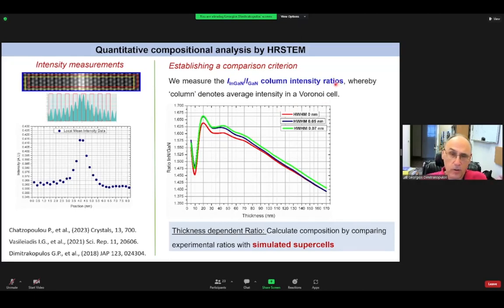But you have to keep in mind that it's not a straightforward thing to correlate this intensity ratio to the composition. You need to do the hard work. You need to do image simulations, because this intensity ratio, even for a certain composition, is not stable, but it changes with the thickness of the TEM foil. So you see here that this is for 100% indium nitride, and outside we have gallium nitride.